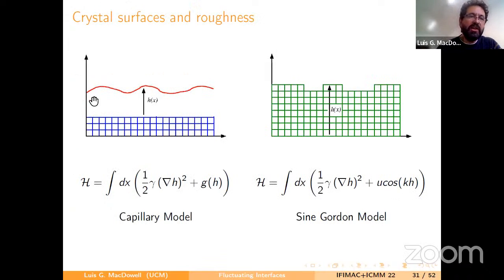It's not, because we've been talking about how to study surface fluctuations in a liquid vapor interface. And we've seen that we can describe those fluctuations in terms of this free energy model, which is called the capillary model. But if we're studying crystal growth, now what we have is rather flat surfaces. And what we see is that the film heights, if you want, you could call this film heights, do not take arbitrary values. They take values that are congruent with the lattice spacing of the solid. So the smart way of studying this is picking your capillary model, but just replacing your monotonous interface potential by a potential which is a sinusoidal function. And this is going to promote your film thickness, or your film height, say, or the surface height, to obey exact lattice spacings. Okay, so it's just the same model with a different potential.